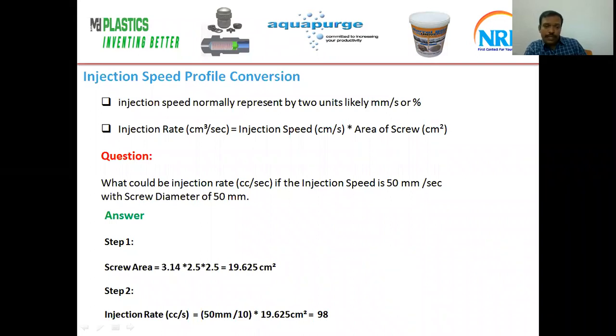First step, we have to find the area of the screw. The area of the screw for 50 mm dia is 19.625 centimeter square. Then step 2, we find the injection rate. Injection rate equals injection speed divided by 10, because I am converting into centimeters. So 5 centimeter multiplied by the screw area of 19.625 centimeter square gives an injection rate of 98 cc per second.